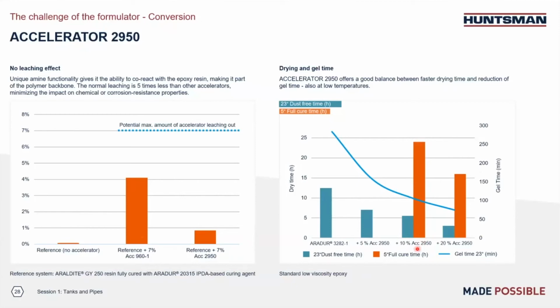If we further increase the loading amount all the way to about 20% loading, we can drop the full cure time to 16 hours. So if we have an example like a floor coating application, which means even at a 5 degree curing condition, we still can apply the coating and work on it on the same day. So that's a very good performance.